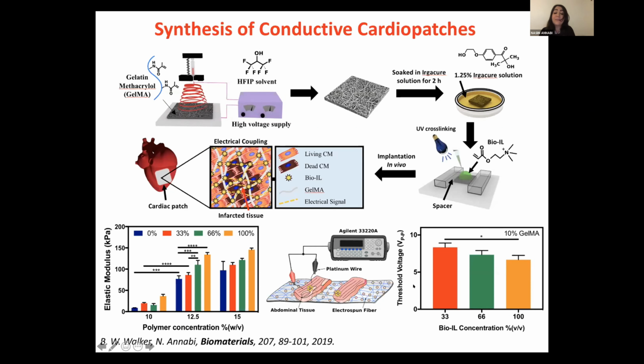And then through this experiment, we calculate excitation threshold voltage, and we found that as we increase the conductivity of the patch we place underneath of the tissue, the excitation threshold reduced. Basically, tissue responds to the level of the conductivity of the patch that we engineer.